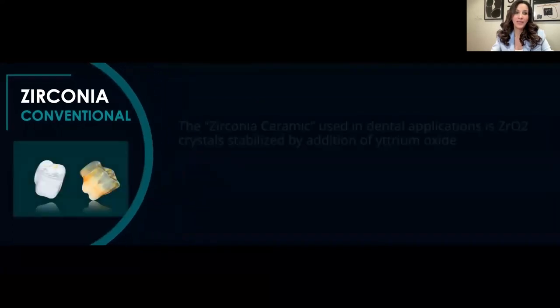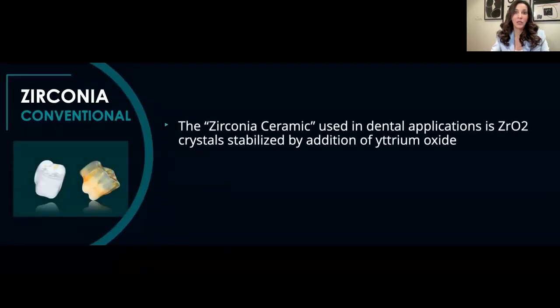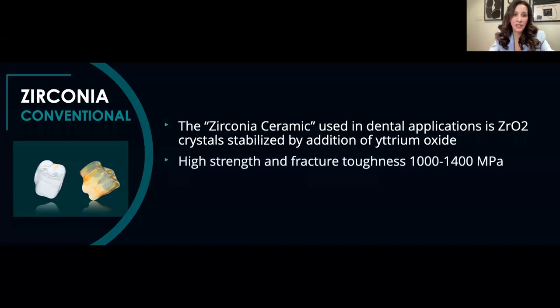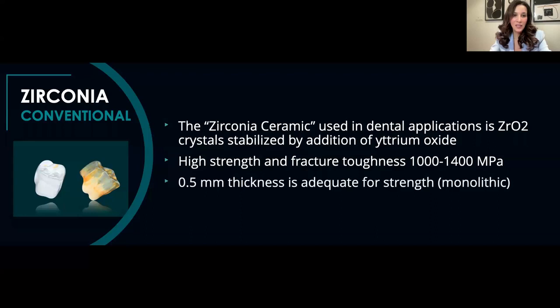What we use in dentistry, the zirconia ceramic used in dental applications, is zirconium dioxide, which is stabilized by the addition of yttrium oxide. So we'll talk a little bit about what yttrium does to zirconia. Now, this material is very, very strong. It has a high strength and fracture toughness that can exceed 1,000 megapascals. And because of this, it could be made very thin, up to about 0.5 millimeters in thickness, which is adequate for strength in its monolithic iteration.